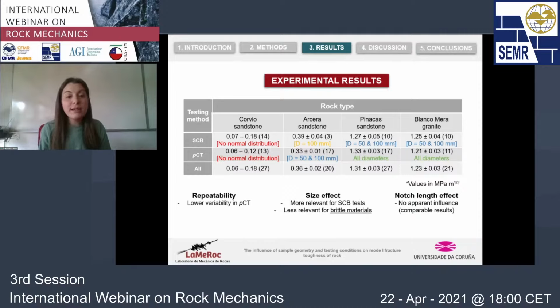the mean values and the standard error of the mean in each case, for the 2 different testing methods and for all the samples that we have tested combining the 2 methods, and the values are given for each rock type. So we see that, for instance, here for the Corvio sandstone, which is the weakest material that we have tested, the values didn't conform to normal distributions neither for the SCB nor for the μCT.